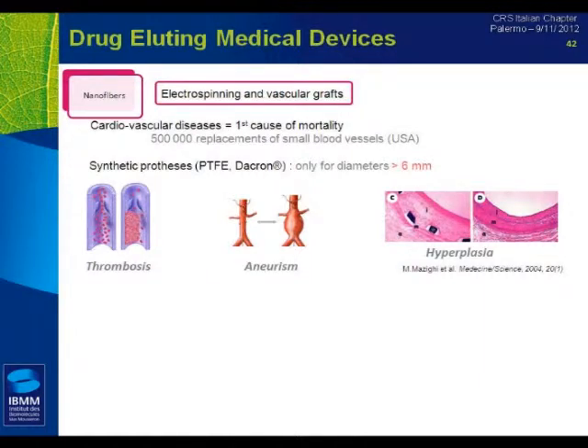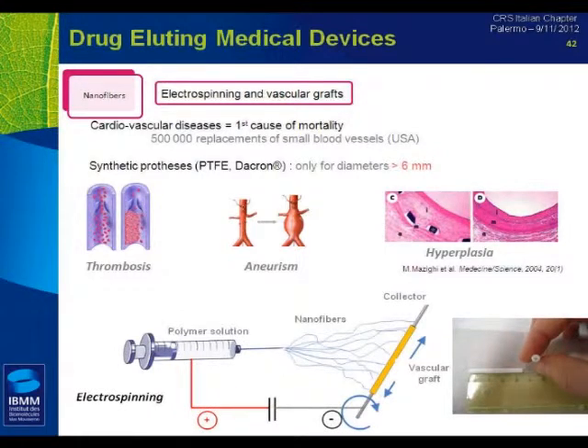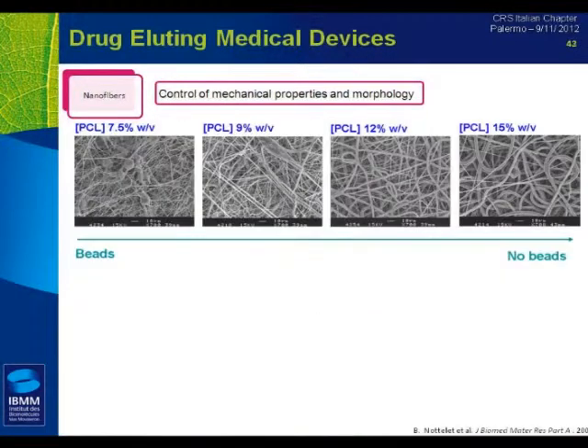And we prepared those grafts by electrospinning of PCL solutions. You can see here the grafts that were obtained, so small vascular grafts, 2 millimeters as an inner diameter. And we worked on the process of the spinning, the various parameters, to obtain morphologies which were controlled, remove all the defects like the beads here. And we did this optimization more in terms of mechanical properties.